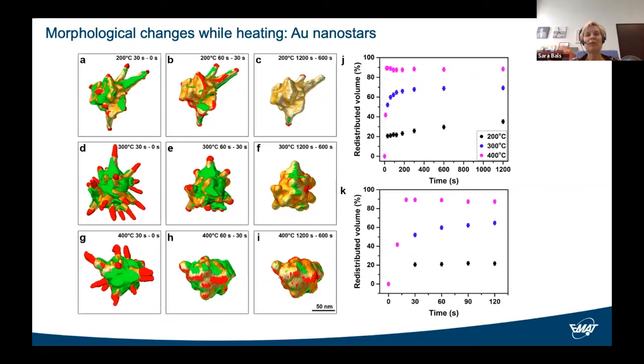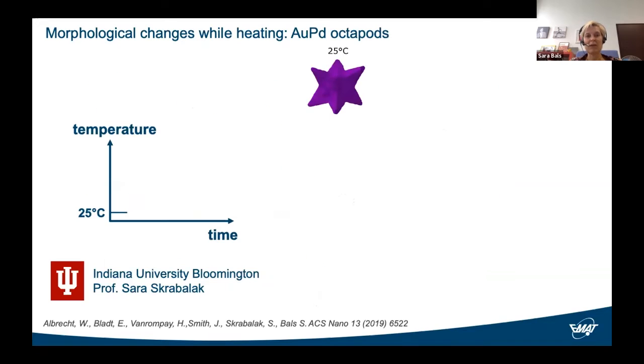So keeping that in mind, we performed another experiment where we investigated gold palladium octapods. And now we're going to be looking at one and the same particle. And each time we're going to be changing the temperature. So we start at room temperature, we collect a tomogram. Then we heat to 200 degrees Celsius. We now keep it here for 2 minutes or so, because we know then most of the changes have occurred. We quench, we acquire another fast tomogram, and we heat again, but now to 250 degrees Celsius, and so on